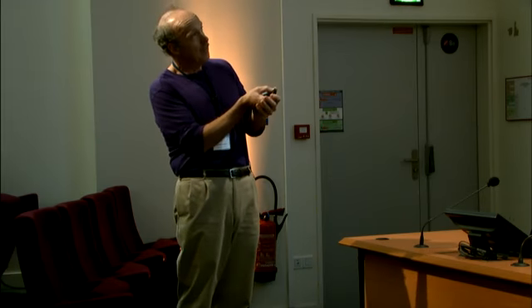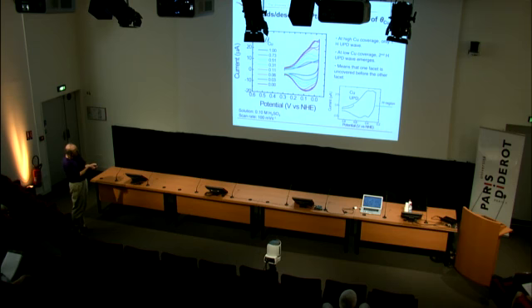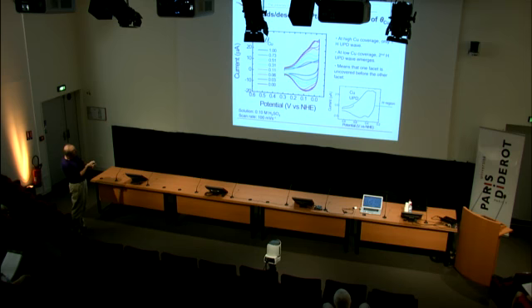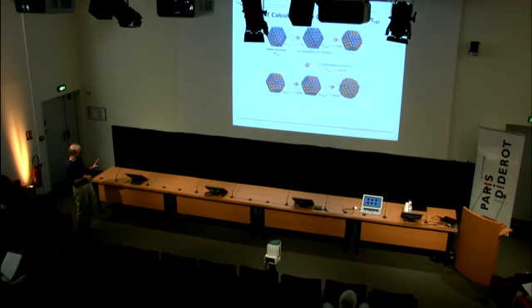And so what you see when theta copper is 1, where we're pulling the electrode out here, is we don't see any hydrogen adsorption or desorption. Why? Because the platinum sites are covered by copper. Up here, where we have smaller fractions of copper coverage, we see first one peak, and then at even lower coverages, a second peak starts to emerge. And so what we say is, this is deposition first on the 100 facet, and then copper deposition on the 111 facet. That's the model.